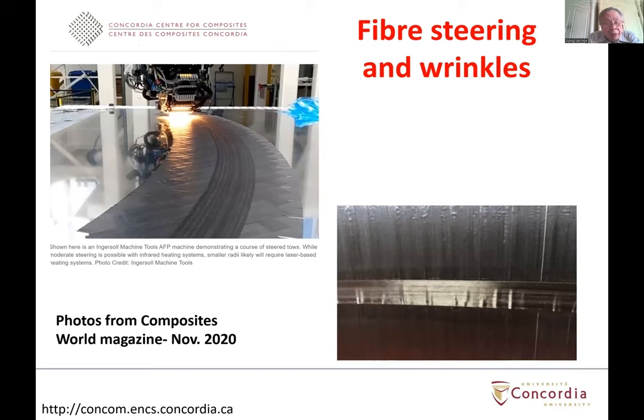Now, the other thing that I feel a lot of people spend time on is the case of wrinkles. A wrinkle is another form of defect, but the wrinkle is caused by the steering. We know that automated fiber placement has the ability to steer the fiber along a certain curved path. The reason people do that is so that you can position the fiber in the direction of the load. That way you have a more load-efficient design, and maybe you can have a lighter structure. But when you do the steering, you create the situation where one edge of the tape is shorter than the other edge, and the fact that it is shorter tends to create wrinkles, and then buckling. In the center, you put a compression load here, and you have the wrinkles.